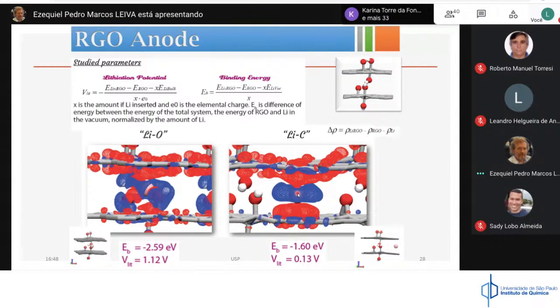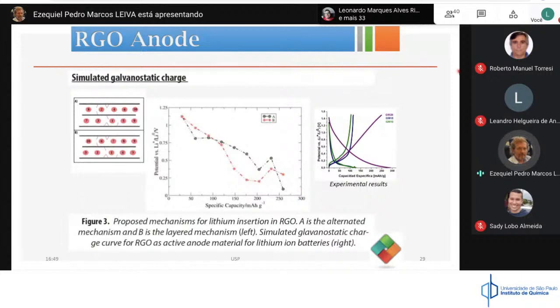So what you can do now is try to simulate the energetics of a galvanostatic curve. In this case, we have taken two layers of oxidized graphite, and we have inserted the ions in a sequence, 1, 2, 3, 4. We have always looked for the lowest energy conditions, and we have inserted different numbers of ions following this sequence. And this is another approach where we have inserted all the ions in the same layer, and afterward we have inserted all the ions in the other layer. This gives you an idea of the energy distribution and the insertion potential as a function of the capacity.